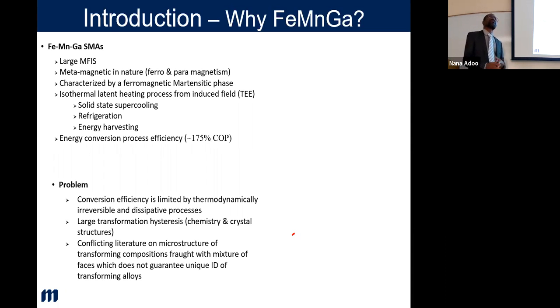Nickel-based materials, or these materials for shape memory alloys, most often, because of this FCC to BCC transition, are very brittle. So it's not easy to engineer them in these applications. Why iron? Iron has been found to be ductile. And if we can minimize this, then we can use this in these applications that we're talking about.